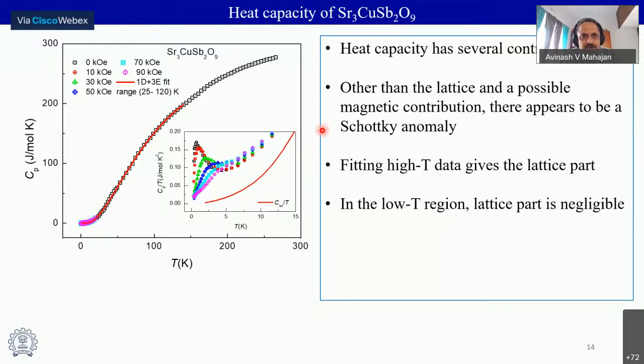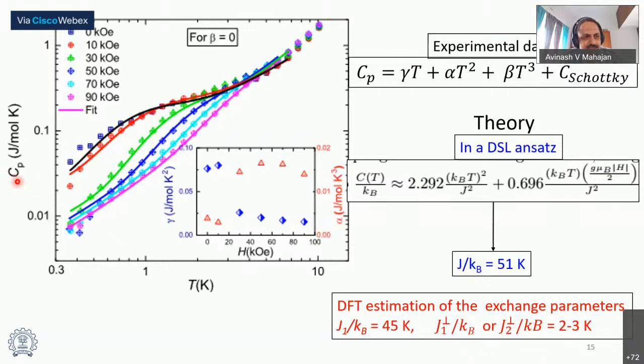So it was possible for us, we found that if you now focus on the low temperature region, so this shows the measured heat capacity as a function of temperature, and this is shown on a log-log scale here. It was possible to fit the measured heat capacity as a combination of a linear, quadratic, and a Schottky term. There's also a cubic term present because of the lattice part. However, in this low temperature region, especially below 2K or so, it is utterly negligible. And if you don't even consider this, one doesn't get much different values of the coefficients gamma and alpha. So the significant result here is that one could fit the measured heat capacity as a combination of a linear term, like you would expect in a normal metal, a fermion-like term, a quadratic term, and then the Schottky term is also here, extrinsic. Okay, so essentially the magnetic heat capacity appears to have a combination of a linear and quadratic term.